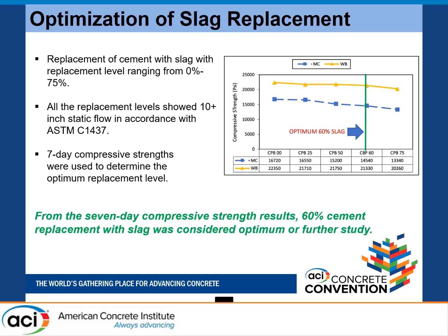But we have chosen 60% replacement level because it exhibited 17,000 psi, and anything above 60% we saw workability issues. We even tried 100% cement replacement too, but workability became a very complex issue. We could not get workability even after adding 10 gallons per cubic yard of high range water reducing admixture. So we thought 60% is a perfect replacement for cement in UHPC systems.